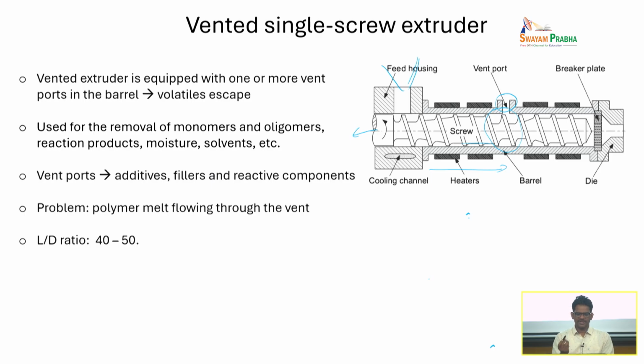So sometimes what happens is that when you do polymerization of a monomer, all the monomer may not be polymerized. You may have still some unreacted monomers and oligomers, which could be highly volatile, okay, at high temperature. So you can remove these monomers and oligomers, reaction byproducts, even moisture sometimes, and then some other residual solvents. All these are volatiles. Okay, so you should have some sort of a vent-like mechanism to remove this.